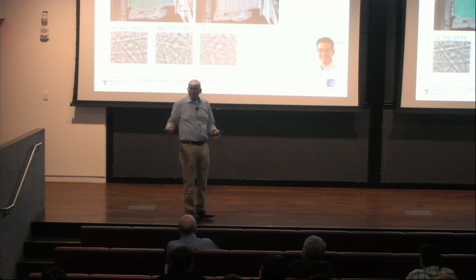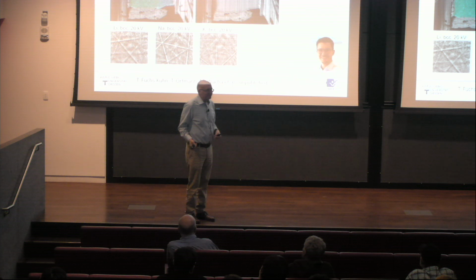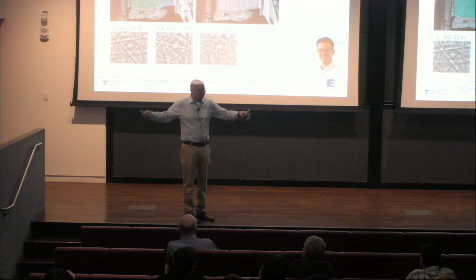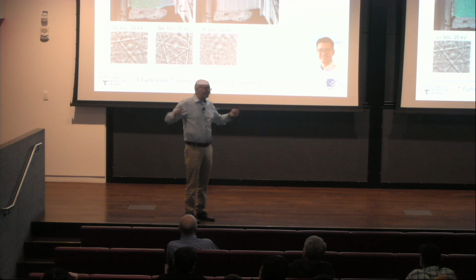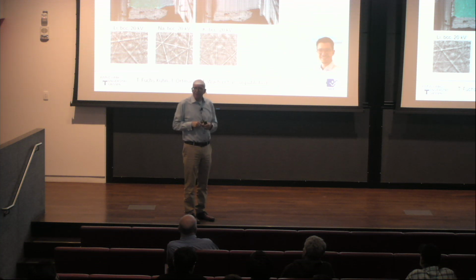Still some questions. We had a meeting with Matt because we tell that sodium is an issue. It degrades the interface. They say, okay, if you have a thick sodium layer, it's good. So there are some questions. I can't tell you, but this is an example that the layers may, of course, improve the chemomechanics. Originally, I thought that, for example, just a polymer interlayer could be good. So far, I think we didn't really succeed in getting a good one.